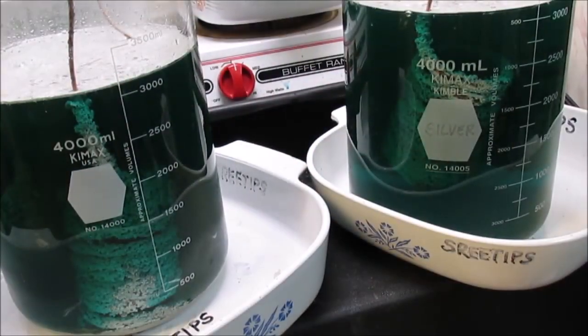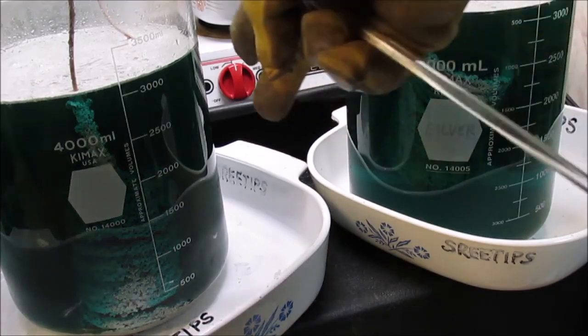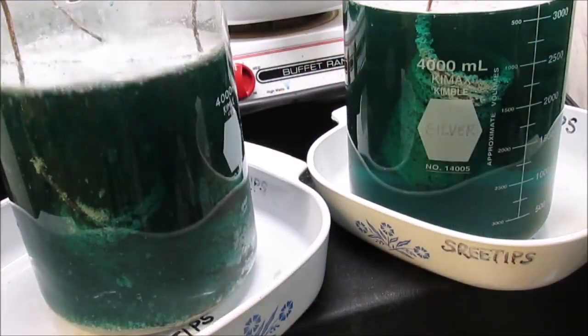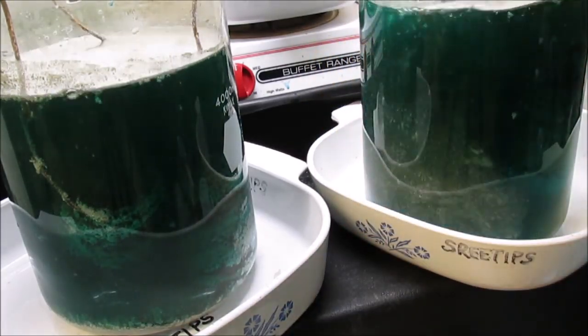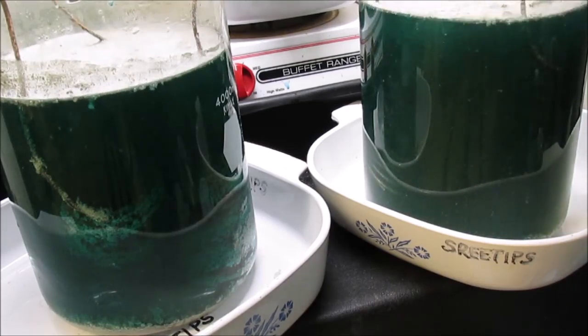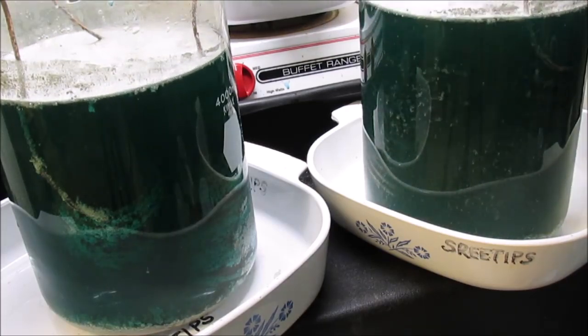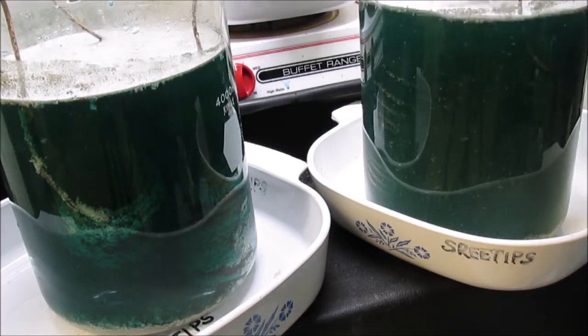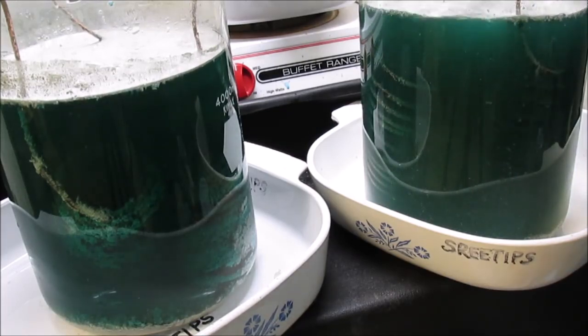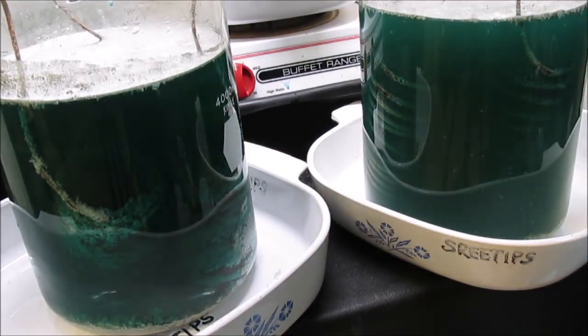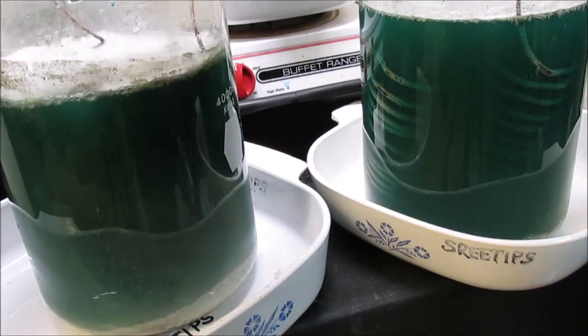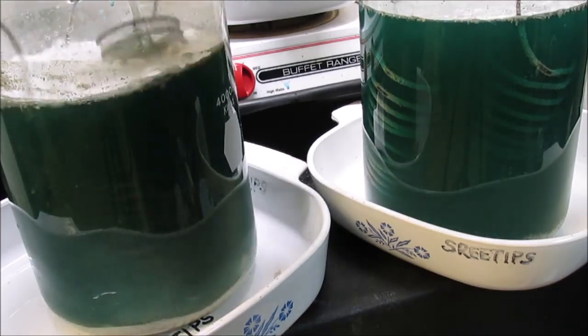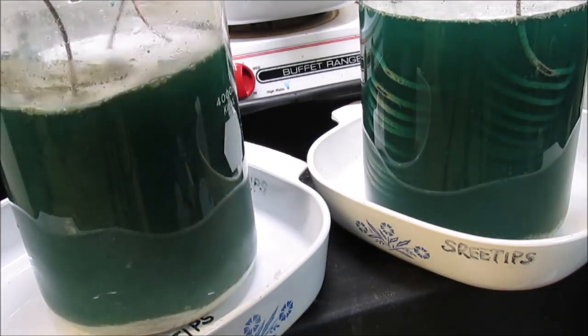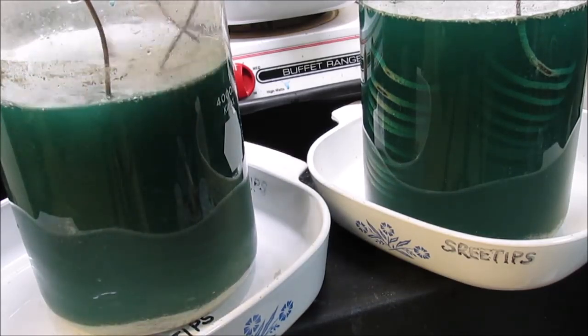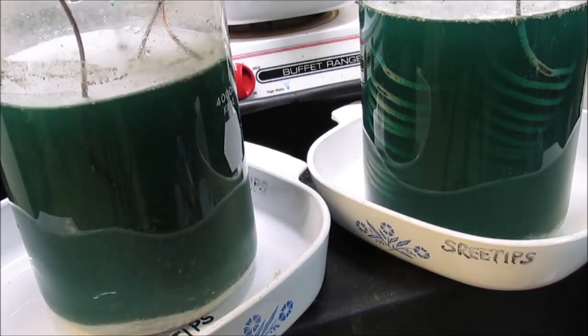It's been about 30 minutes since I added that fresh copper, and looks like things are going okay here. Stir it up a little bit, and I'm getting a little bit of heat and a little bit of stuff floating on top. That's probably from the nitric acid that I added earlier to try to jumpstart the cementation process. But that'll get used up in here. I didn't add that much, so we should be okay. But everything looks like it's going okay now.